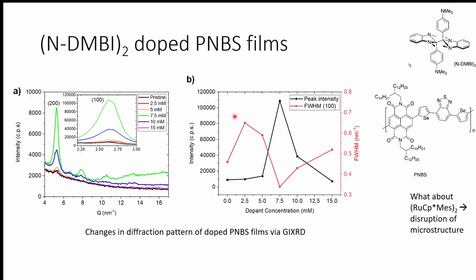Now, I wanted to characterize the microstructure when adding this impurity throughout the film, and see what is happening to my order. This is not a very pretty picture for anybody who's an inorganic chemist, but for us organic polymer people, it's amazing that we're able to get nice images. Normally, some people use a synchrotron, but we didn't have access to that at that time, so I just used a regular XRD instrument to get these patterns on the film.